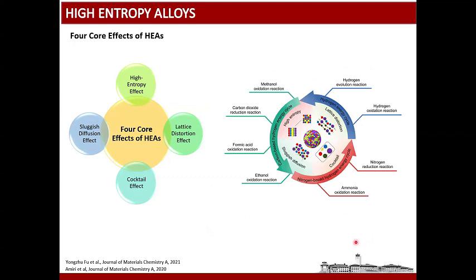And when you prepare a high entropy alloy, they introduce these 4 core effects. One of them is the high entropy effect, which stabilizes the structure. Another one is the lattice distortion effect, which introduces different energy sites or binding sites on the surface for different catalytic applications. Then there is the cocktail effect. In the cocktail effect, since we are bringing at least 4 or 5 metals with different properties, different orbital structures, different electronic structures, different d band levels, this cocktail effect will introduce a mixture of these properties at the nanoscale.